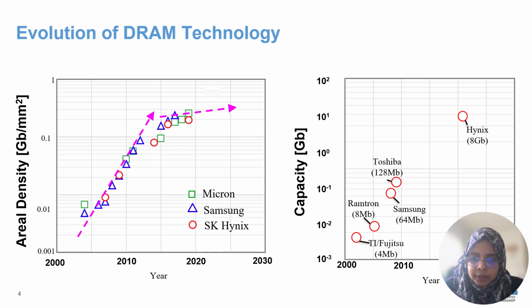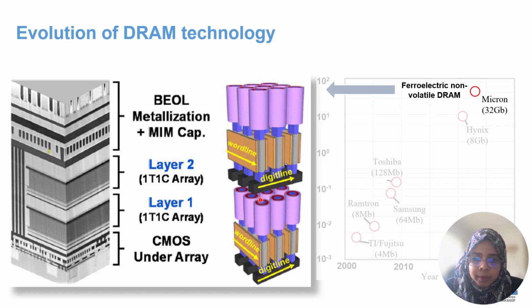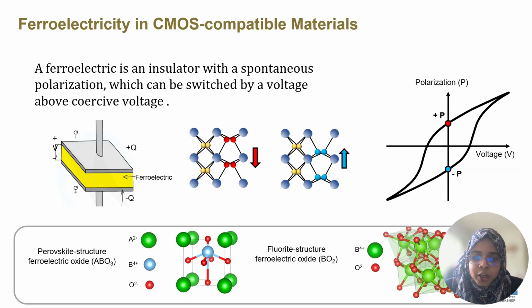If we look at capacity, it is increasing, but still we had a maximum of 8 Gb DRAM capacity. But a major breakthrough happened when Micron showed a 32 Gb ferroelectric non-volatile DRAM architecture, where they showed a dual layer architecture. What they did here is that they replaced the traditional capacitors in DRAM with ferroelectric capacitors. This change makes it a non-volatile DRAM architecture, through which they were able to gain 32 Gb capacity in their non-volatile DRAM.